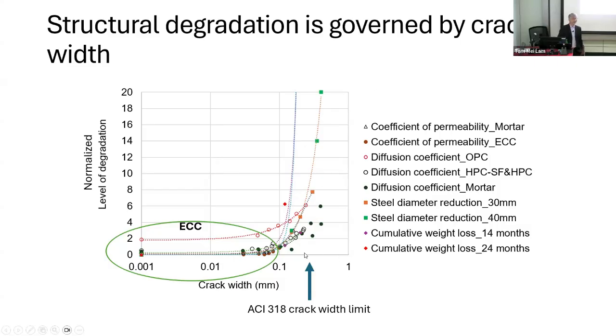Okay, and that exactly is why ACI eliminated it, because structural engineers said, I can't really reliably design my structure that way. So there is no longer, in the new versions of the 318 code, this requirement of crack width. There is a change to number of rebars and their spacing. And that's it. Everybody can put in and measure the distance, and you can satisfy that. So you are not at risk of your engineering license, right? But it doesn't really actually cure the problem. The problem remains here in terms of durability.